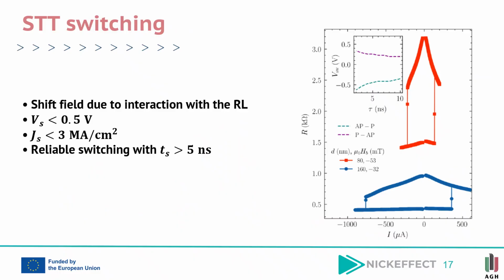After fabrication of the MTJ nanopillars, spin transfer torque (STT) switching measurements were performed to evaluate the switching performance of the optimized PT-free MTJ devices. The graph on the right presents representative current-induced switching loops measured for MTJ pillars with diameters of 80 nanometers in red and 160 nanometers in blue. Clear switching between the parallel and antiparallel resistance states is observed for both device sizes, confirming efficient STT-driven magnetization reversal